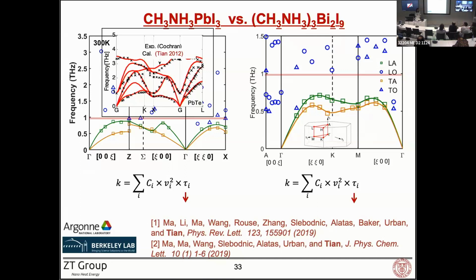So these soft modes would give a small slope and small group velocity. In this case, we would expect an even smaller group velocity. So without even measuring the thermal conductivity, we already predicted that the thermal conductivity of the second material will be even lower. And we did confirm that by performing the measurements.